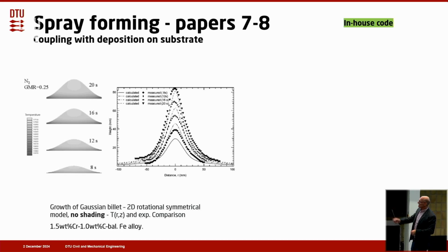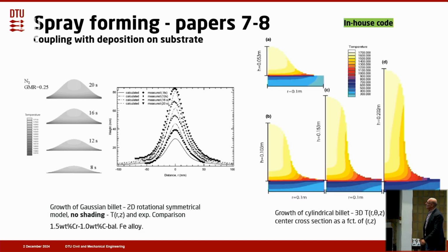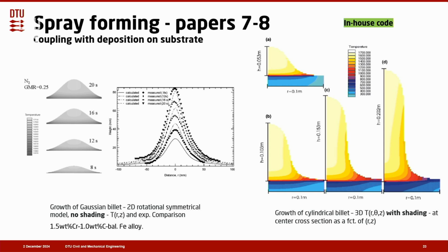You see some results here. Building a Gaussian billet. This is where you have the atomization point right above where you build. Then you just get a Gaussian billet due to the distribution. But if you want to make billets where you have shooting from an inclined, you could say, position, then you get a billet like this, and this is what you see here. This was a growth of cylindrical billet, and here we needed to take the shading effect into account.